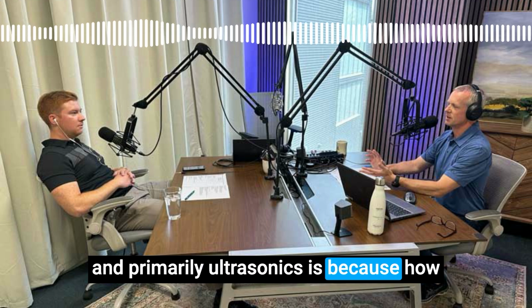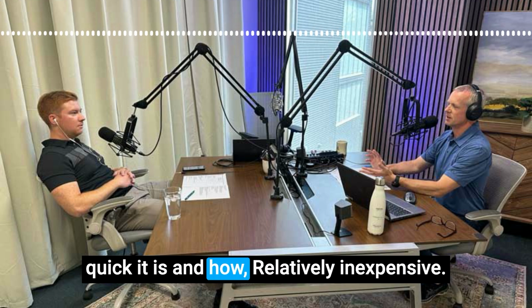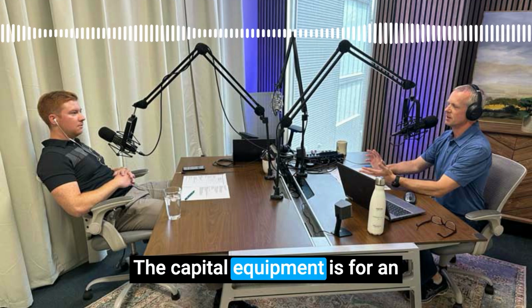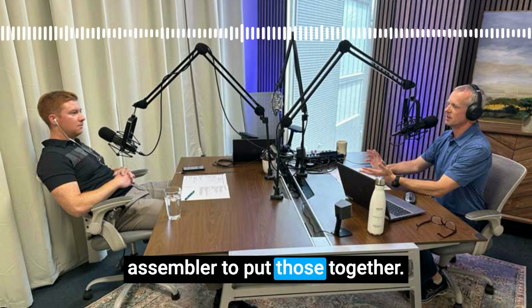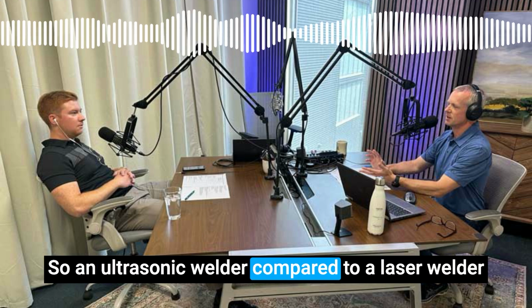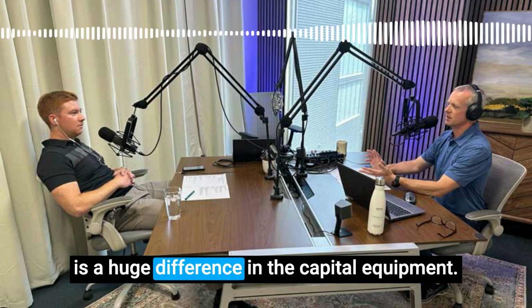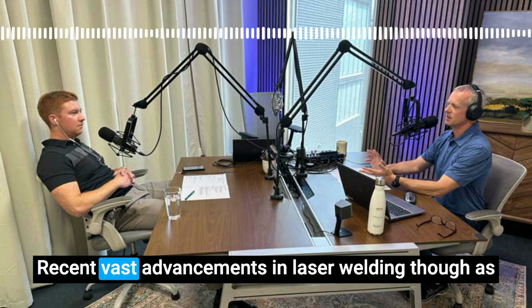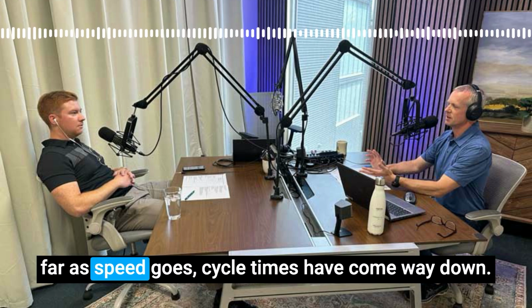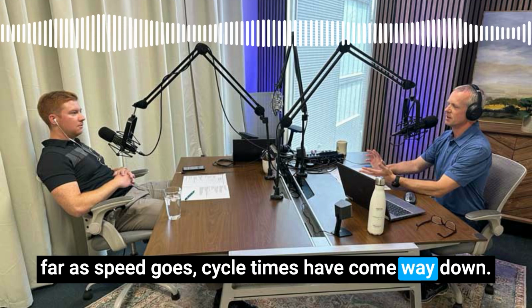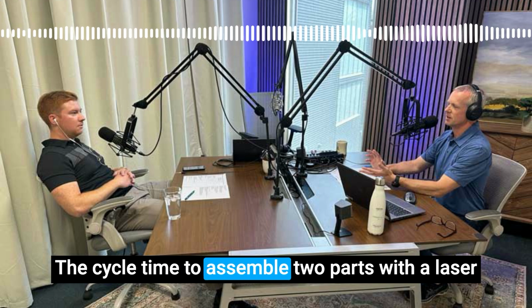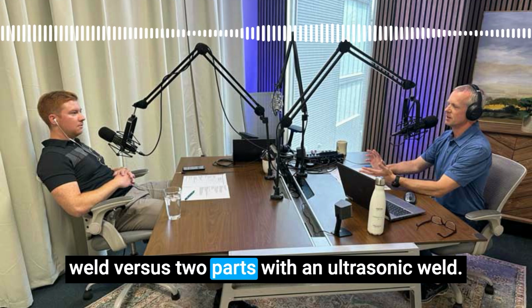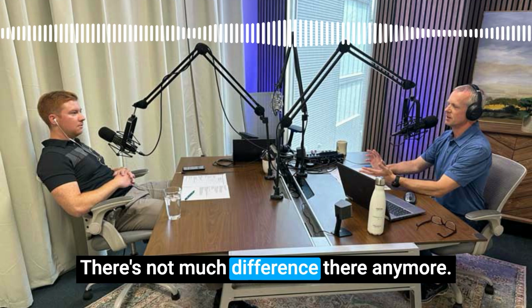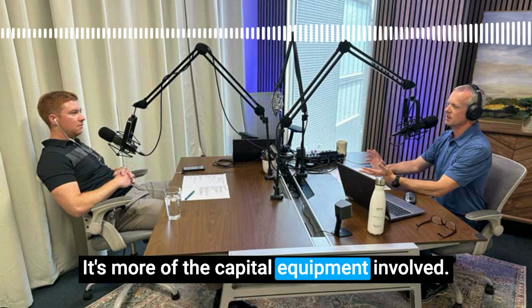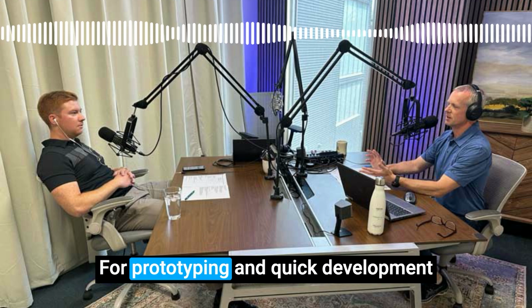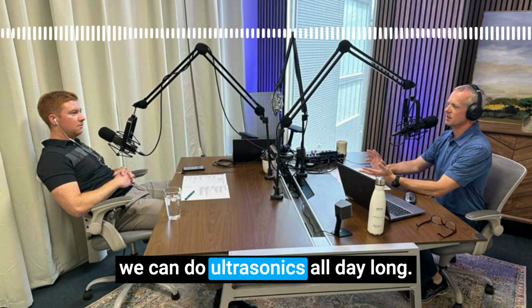primarily ultrasonics is because of how quick it is and how relatively inexpensive the capital equipment is for an assembler to put those together. An ultrasonic welder compared to a laser welder is a huge difference in the capital equipment. Recent advancements in laser welding, though, as far as speed goes, cycle times have come way down. The cycle time to assemble 2 parts with a laser weld versus 2 parts with an ultrasonic weld, there's not much difference there anymore. It's more the capital equipment involved. For prototyping and quick development, we can do ultrasonics all day long.